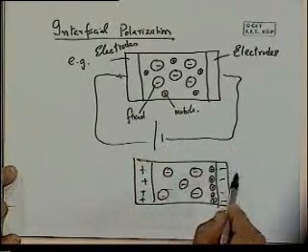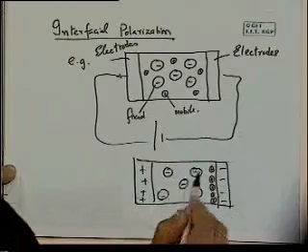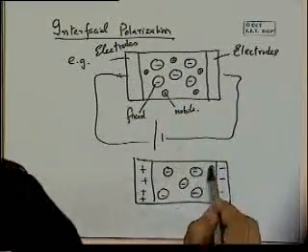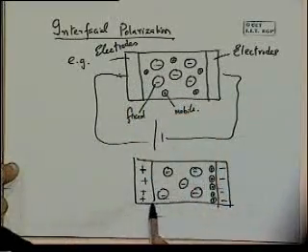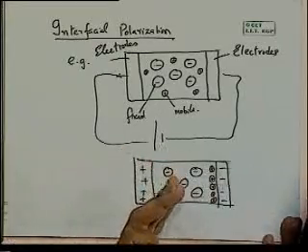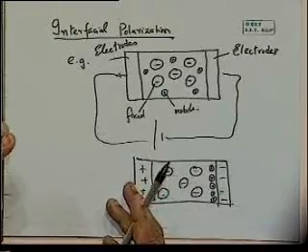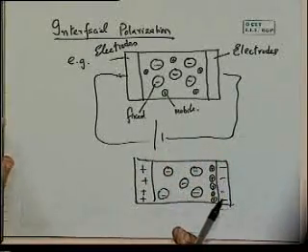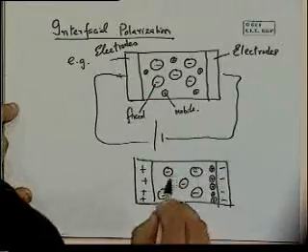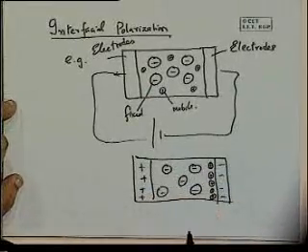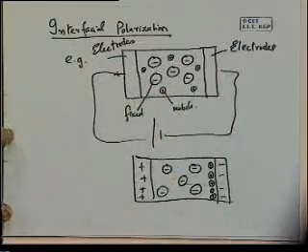Now, these ions simply can't cross over into the electrode, and as a result, the separation and the dipole moments that would have been here are very different. Now I've got them all piled up here, and with respect to the negative ions here, we've got a whole different set of dipole moments. They've all been moved far away, on average, from their nearest neighbor, whatever negative charge was there. They've drifted. And it is these additional dipole moments that are created that contribute to interfacial polarization. That's one mechanism.